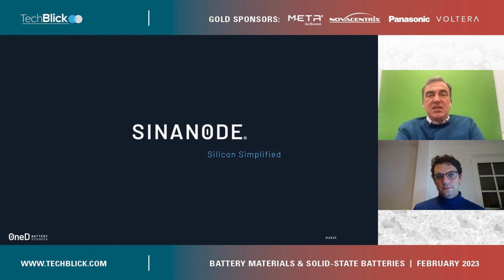But at the end of the day, it's not the percent silicon that matters. It's two things. One is what is the reversible capacity? Because it always makes me laugh when people talk about silicon dominant when they have 60% silicon in an amorphous carbon, because it's really 60% silicon and 40% inactive materials. So on the one hand, the silicon is partially used, and on the other hand, you put in a lot of inactive materials. The second problem is that you get cathode limited.